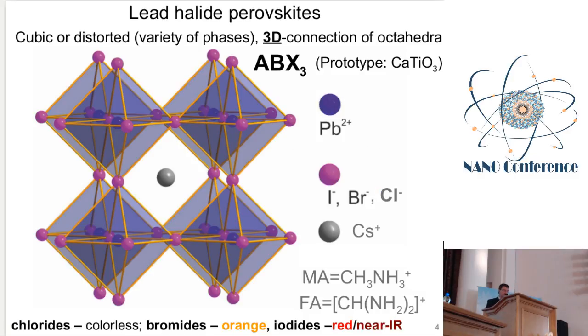And now I would like to make a short introduction to this class of novel materials. These are solution processed semiconductors, lead halide perovskites. They have a cubic crystallographic structure, with a general formula similar to their oxide perovskite analogs. In this formula, the last element plays the role of anion, and typically we work with halides. By changing halides like chloride, bromide, and iodide, we can broadly tune the band gap of this semiconductor material.